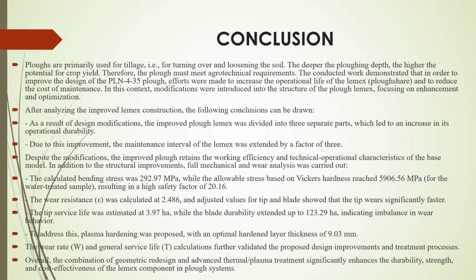20.16. Wear resistance was improved, as you can see in our slides, and general durability of the blade reached up to 123 hectares, showing significant enhancement compared to the original design. Plasma hardening with a 9 mm hardened layer further increases strength and resistance to wear. Overall, the combination of the geometrically designed and the heat plasma treatment has made the plowshare stronger, long-lasting, and more cost-effective for agricultural use. Thank you for your attention.